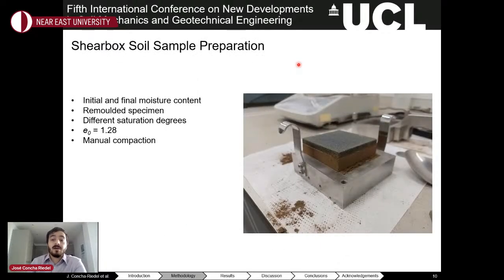For the shear box test, the soil was prepared with a known initial moisture content. The sample was then molded into the shear box mold using a specific amount of soil to achieve an initial voids ratio of 1.28. Different saturation degrees were tested to assess the effect of saturation on the shear strength. All samples were manually compacted and put into the shear box test immediately. After the samples were continuously sheared until failure, a moisture content sample was retrieved from the failure plane to compare the initial and final moisture contents. These values ranged between 0.5 and 2.5%. For this test, three normal stresses were used, 40, 177, and 354 kPa, which are common service conditions for adobe walls.